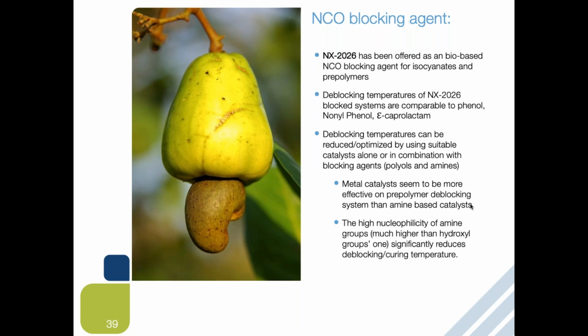And from the study, we have learned that using catalysts and blocking agents are very effective methods to reduce and optimize your system. In terms of catalyst, metal catalyst is more effective than amine-based catalyst. When it comes to blocking agents, amine and polyols were studied, but amine, having a high nucleophilicity, seems to be much more effective when you're trying to reduce the deblocking temperature. And of course, the blocking agent and catalyst can also be blended together to achieve further reduction in deblocking temperature.